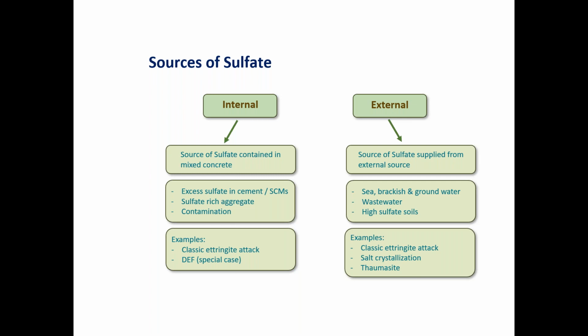So this is an attack within sulfate-rich aggregates and potential contamination. And there are some things that people may want to add to concrete, which in small amounts are perfectly fine and useful, but in large amounts or in contaminated sources, they can also cause this. So in the examples of the types of internal attacks that you'll see, and again, this isn't an exclusive list, it's the classic ettringite attack, as well as delayed ettringite formation. The other type of source is going to be something that comes from the environment, comes from outside of the concrete, and works its way into the concrete over time.